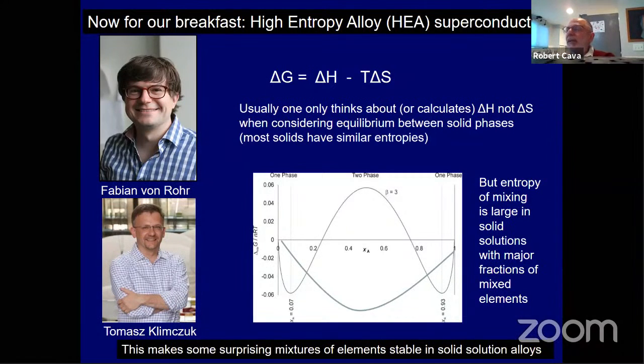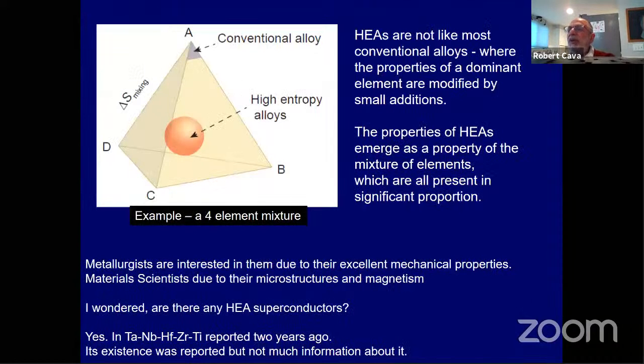But it turns out that there are some substances that are stabilized by a large entropy of mixing, and that's what high entropy alloys are. They are substances that are stabilized by high entropy of mixing of their constituents. This is a new field in metallurgy that's been studied for the last 10 years or so. These high entropy alloys, which have roughly equal proportions of multiple constituents, have mechanical properties substantially different than those of a conventional alloy. Take carbon steel, where you have a small amount of carbon in iron and you get a different kind of mechanical character. These things have a dramatically different character.